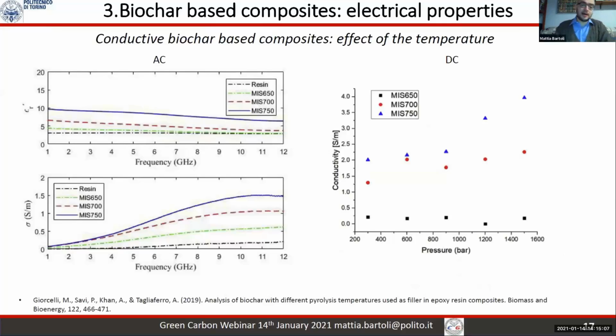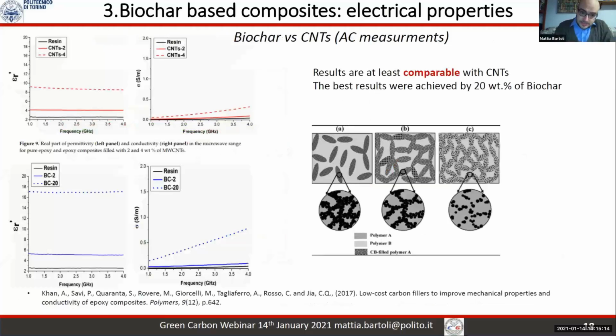So, CNTs and biochar for composites containing carbon materials. As you can see, CNTs at a concentration of 2 and 4% displayed a good conductivity in the composites. Nonetheless, biochar in higher concentration, up to 20%, can outperform, at least at higher frequencies, the results obtained with CNTs. And this was due to the different distribution of carbon particles inside the polymeric matrix. CNTs display the tendency to create agglomerates, while biochar is very easily dispersible in all polymeric matrices.